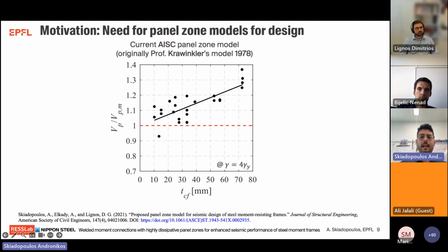Finally, to potentially exploit the beneficial aspects of panel zone shear yielding, a reliable panel zone model is imperative. And by utilizing the test data that I described before, we compare the prediction of the American code as Vp, and we normalize it with the experimentally assessed panel zone shear strength as Vpm. So what we see is that this ratio tends to be 1.4, which means that the American code overpredicts the real panel zone shear strength at 4 gamma y by more than 40%. And this is especially critical when we utilize panel zones with thick column flanges. Therefore, to mobilize the panel zone in seismic design, a more robust panel zone model should first be developed.